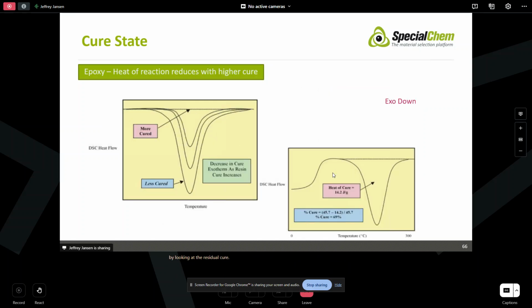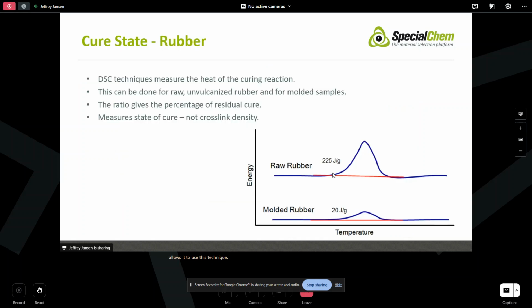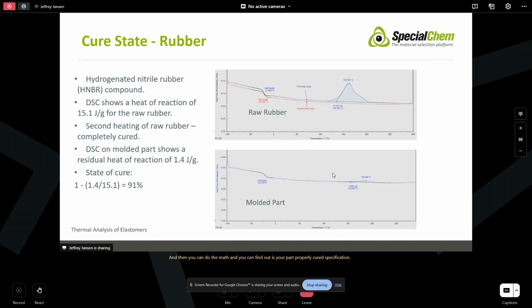Now, not all thermosets react in a way that allows you to use this technique. Rubber does. If we're talking about that EPDM rubber, we can do the same type of thing. Here we have exo down, but we simply measure our raw rubber, that heat of the reaction. We measure the heat of the reaction left in our molded part. What we used to do is measure multiple locations on the part to understand if the part is evenly cured or cross-linked, and then you can do the math and find out if your part is properly cured to specification. And this again is just the same. This was EPDM, and this is a hydrogenated nitrile rubber material.